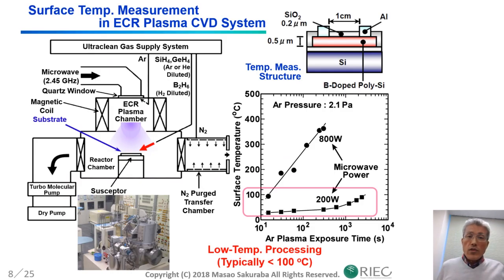Here, I'd like to show our plasma CVD apparatus for low temperature epitaxy. Low energy argon plasma is generated by electron cyclotron resonance (ECR) and induces surface reaction of reactant gases such as silane, germane, and so on. This has enabled us to achieve epitaxial growth of group 4 materials and in-situ doping without substrate heating.